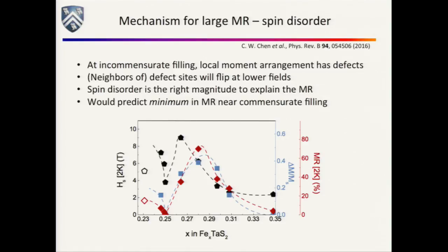If that's true, then you should only really see these things when you're at some funny incommensurate filling level. In a follow-up paper, Shiwei, the student with Professor Morishan, grew a bunch of samples at different compositions, which is a laborious task, but did it. The red is the magnetoresistance data. The magnetoresistance really does have a very sharp minimum near a quarter. They believe it's got a minimum near a third. And in between, at these incommensurate levels, the magnetoresistance actually gets big.